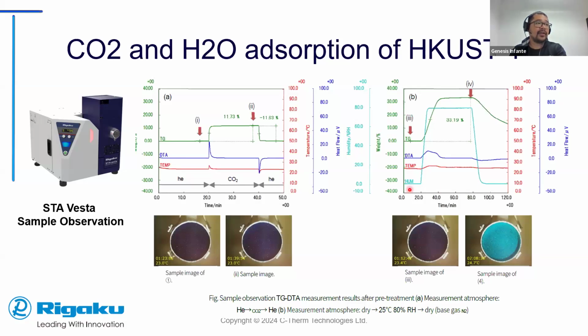And you can see here, there's different graphs. There's temperature. You can see that they're not ramping up temperature, it's room temperature. There's a DTA, DSC signal, and then this is the thermal gravimetric signal. As you're adding the humidity, at this step right here, you can see that there is an increase in the mass. Again, it's pretty straightforward, meaning water is being absorbed. And then as you can see here, as the water is being absorbed, there is an exothermic event. There is heat generated, and you can see that also the temperature increases right there.